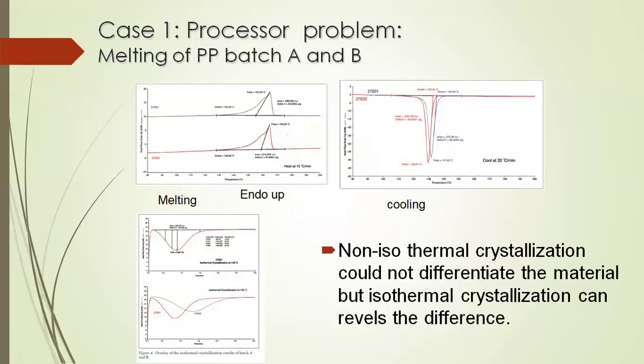I told you how to use TGA in a similar case. Similarly, this is a processing problem. A PP batch was showing some different properties, and in quality control, one batch passes and one batch fails. Then that person did a TGA. It did not give any information because the filler content was similar. Then he did a non-isothermal experiment, which again did not reveal any information because the material was similar, with only a small difference in the crystallization.